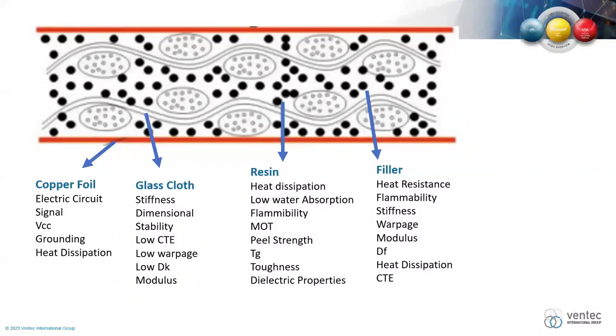Some have lower or higher moisture or water absorption. For instance, polyimide is a very hygroscopic material, and fabricators have to basically desiccate the prepregs and bake the cores to get as much of that moisture out of the material before they actually laminate it together. The flammability rating, the MOT, is it a 130 MOT or a 155? Different coppers have different peel strengths to the resin. And obviously that resin would affect the TG, the toughness, and obviously depending on what type of filler we put in there, and even the glass will affect the dielectric properties themselves.